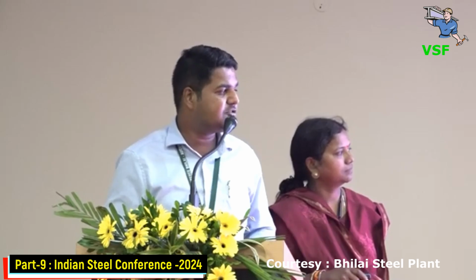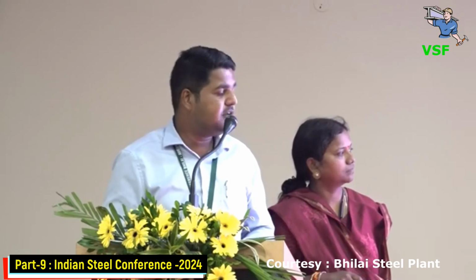So we have tested for GWPI, that is global warming potential index, to see which mixes are performing structurally better and which mixes are performing better from an environmental point of view. We have calculated CO2, CH4, N2O, and we took a 1 kilometer stretch and used that material, and tested what carbon emission the materials produce if we use them for a 1 kilometer stretch, what quantity we are using, and how it environmentally degrades. So the better performing result is hybrid mix 2, with 54.37 kg GWPI.